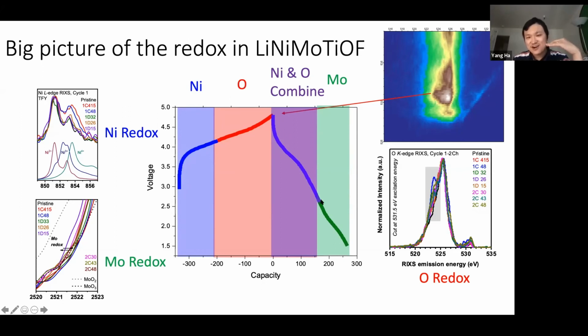And when you discharge it, the oxygen redox and the nickel redox kind of mix together, and at a low voltage, you can see a tiny molybdenum redox. So with this technique, we can really isolate the contribution of different components in a high entropy or whatever cathode materials we have. So this is a really powerful technique for those battery scientists.